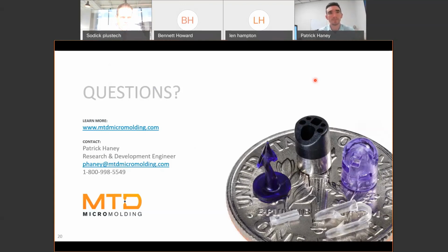When it comes to micromolding them, sometimes they can have higher injection pressures, right? Especially the soft block versions of TPU, because the soft block versions end up acting more viscoelastic. So the more viscoelastic your material is, the more compressible it is, and suddenly your injection pressures are much higher. So when it comes to filling thin walls or long aspect ratios, that is one of the polymers that might fit into the category of higher pressures required, right? But